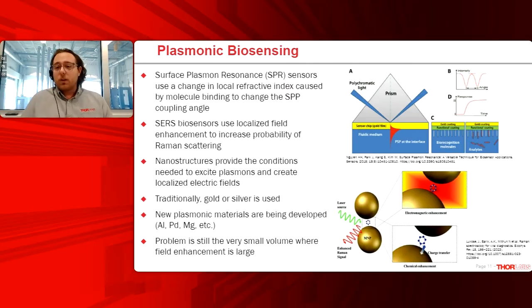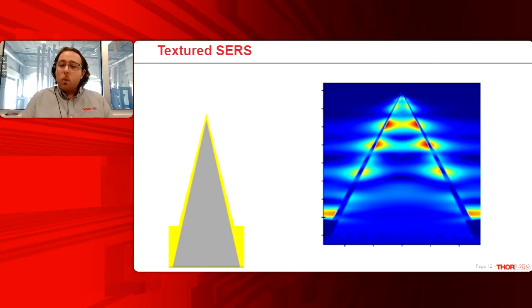And this leads to one of the problems that we see in SERS, which is repeatability. Generally, there are SERS substrates out there that can perform very well in one area, but if you move over a couple millimeters, it may not perform as well. And these are due to these hotspots not being very uniformly distributed. So the thought we had was, what if we use our textured substrates and coated them in some gold to create these plasmonic nanostructures? And in this case, we can create a textured SERS substrate.